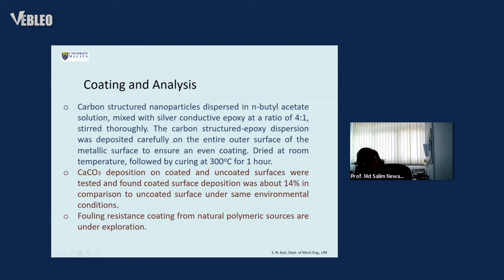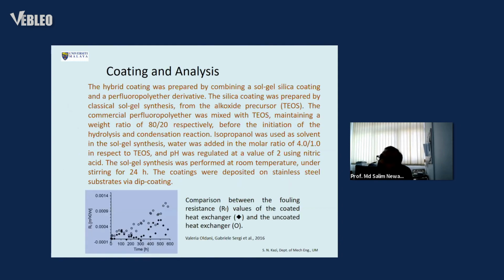And then in this case, by adding a graphene coating, a polymeric graphene coating on the surface composite, we find that only 14% of the deposits on the surface is noticed in comparison to without any coating. More research work is going on at this time at the University of Malaya by exploring polymeric sources for fouling resistance coating, so that if it is a conductive polymer, then it can be used. Another research we explored here is that with the addition of a surface coating with the composite, it can also reduce the resistance and prolong the induction time, so that the heat exchanger can withstand a longer time.